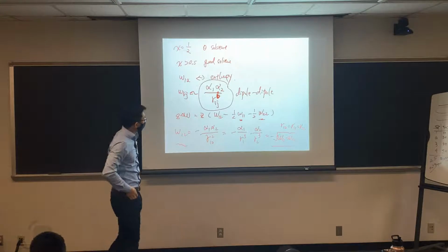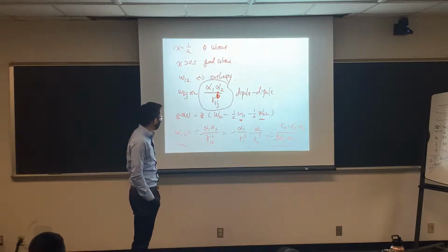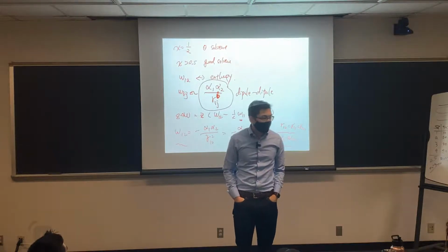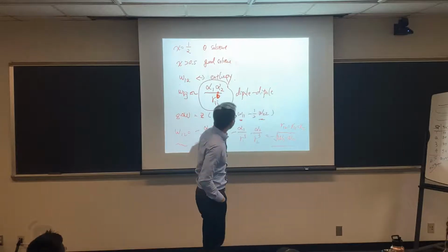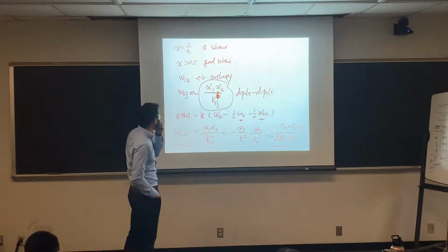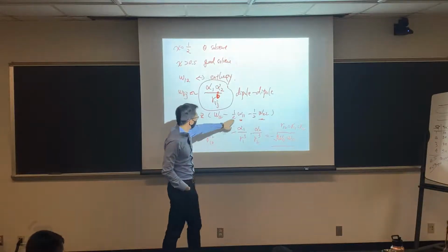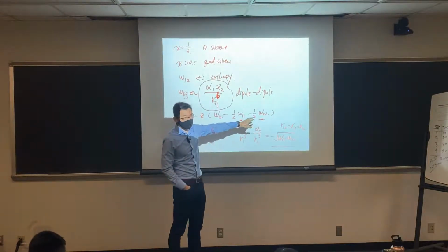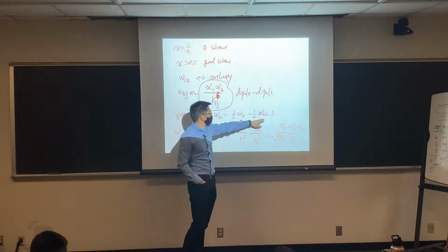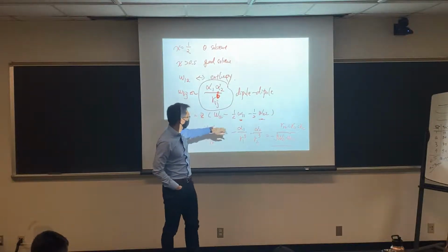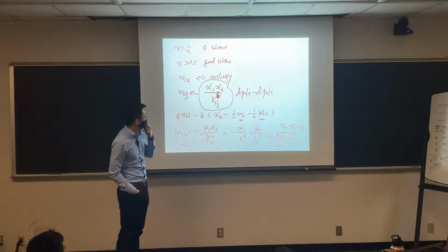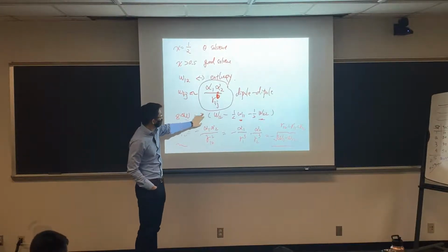These are some of the older lecture notes, but still valid here. We're going to discuss a little bit how we understand this chi parameter. If everybody recalls, when we define the interaction parameter between two species, we talked about W11 as the interaction between the same molecules, W22, and W12 as the interspecies interaction. That's how we define the Flory-Huggins parameter, right? And Z is its closest neighbors.